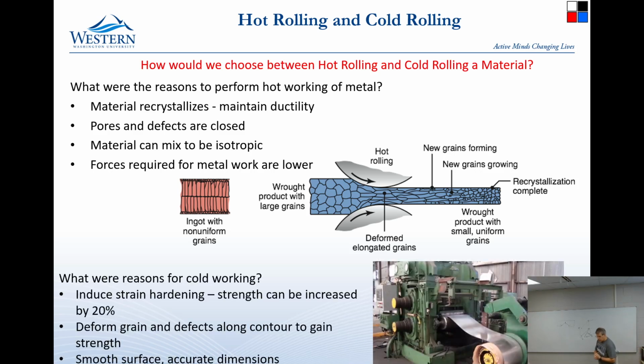If we do cold rolling, just like with other cold forming, it gets us to the right, final shape. It can have sharper edges. It is not going to have scale that grows on it, but we are limited in how much we can strain it. We can strain it about 20% before we have to do something to increase the ductility again. So we can heat treat it or use a number of processes like that to try to recover ductility.